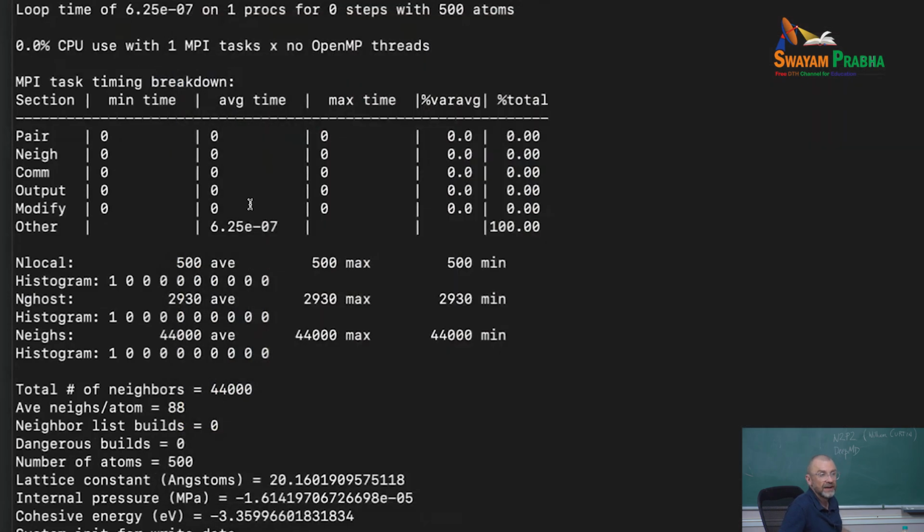So now, how do I compute the formation energy of a vacancy? For those who have looked and the others, how do I compute? So I have aluminum. Now I know that my potential predicts a lattice constant. This would be 4.032, right? And the cohesive energy of 3.36. Now, I want to look at defects.